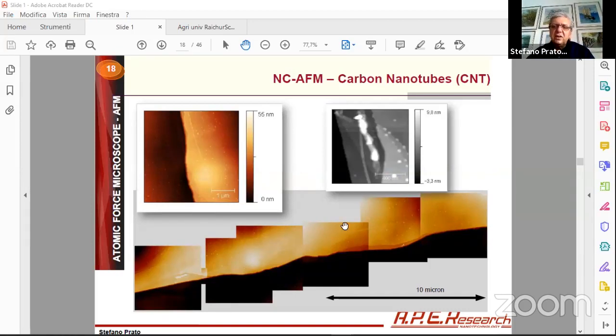So it's not very easy to have a system that can, at the same time, perform a very long range image like this one and have a good resolution. For example, some AFM provide different scanners for different resolutions, okay? This is not good, because during the measurement you cannot mount a high resolution scanner, because otherwise you don't see the Z, but having a large area scanner, it's not possible to mix. So this is a limitation that we, with our experience, try to overcome, and we propose this solution in our instrument where you can change the resolution and accuracy of the system depending on the needs of your experiment. So this is a very tough image to obtain, such a long single wall carbon nanotube in one shot.